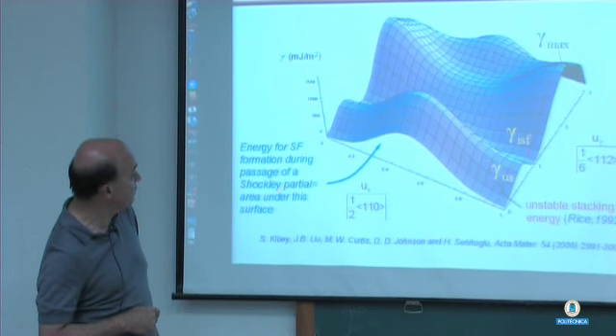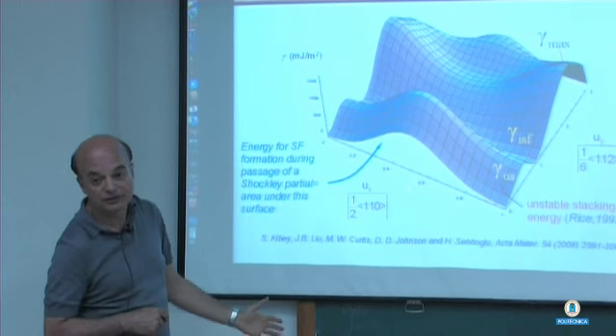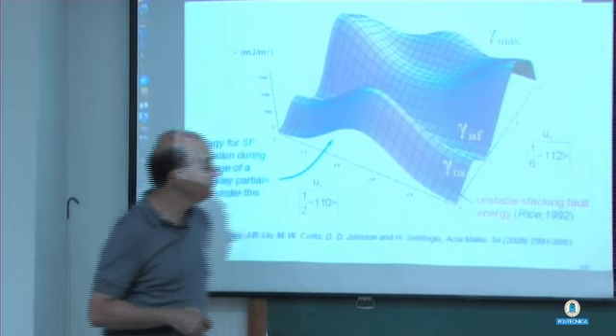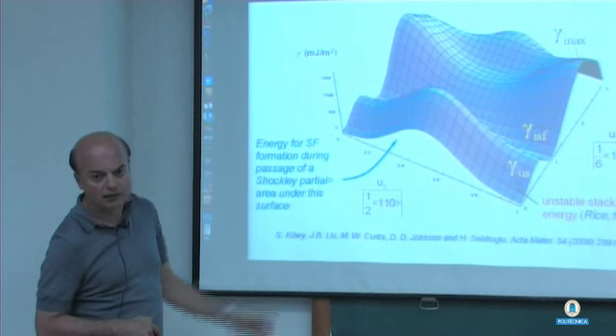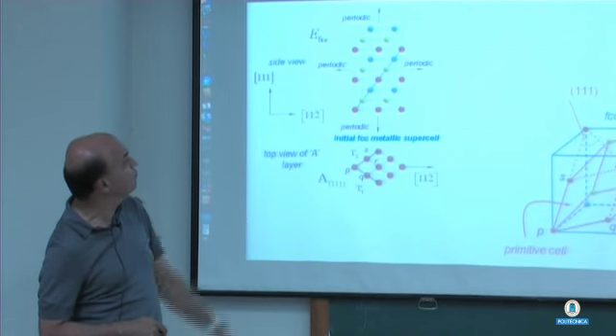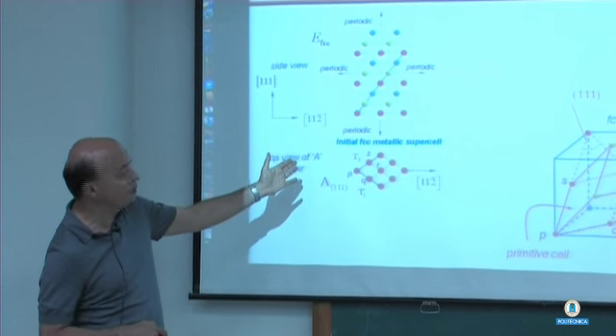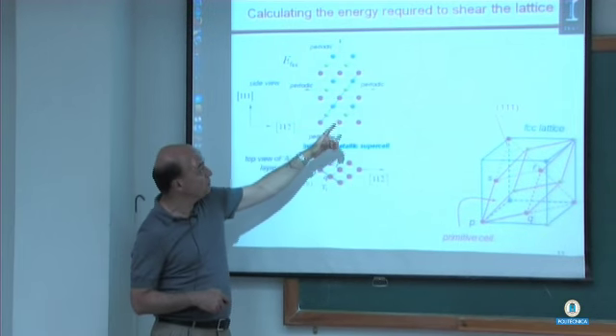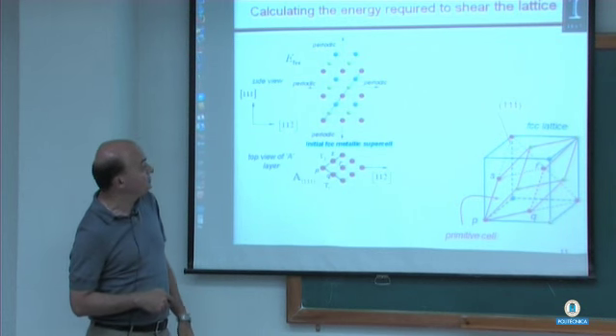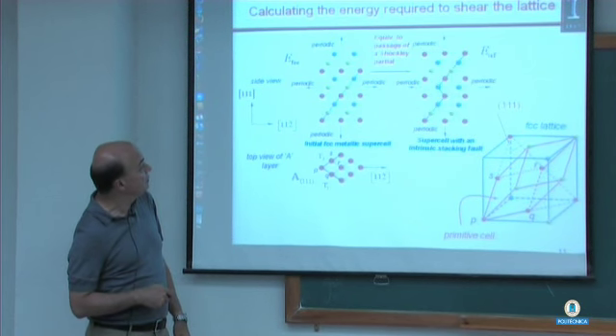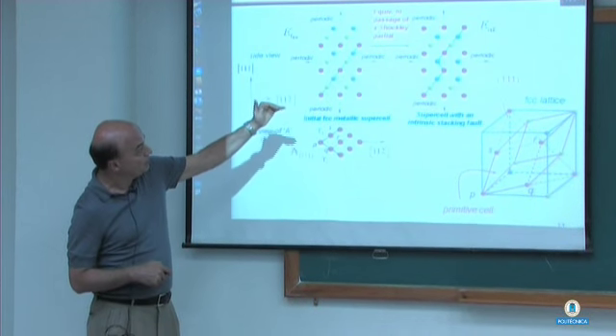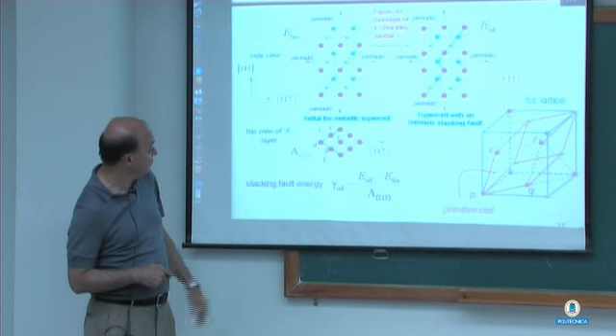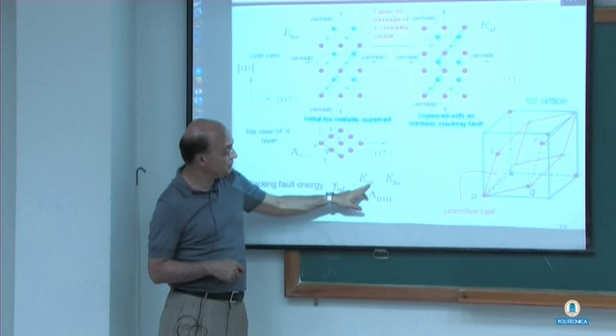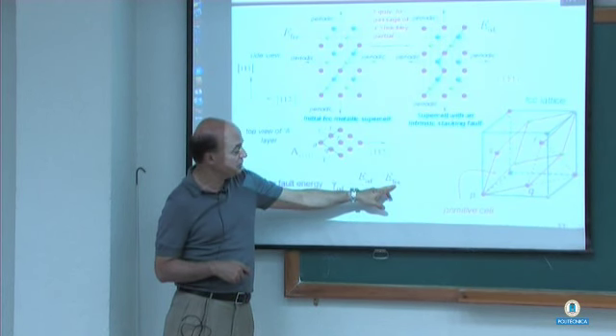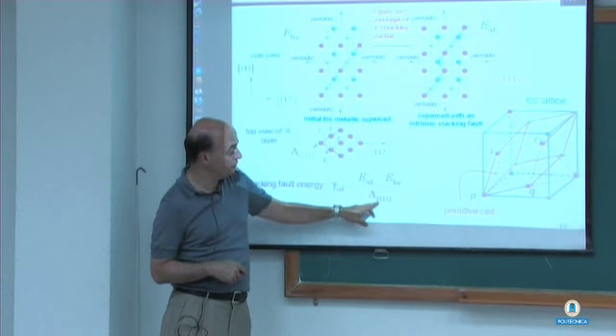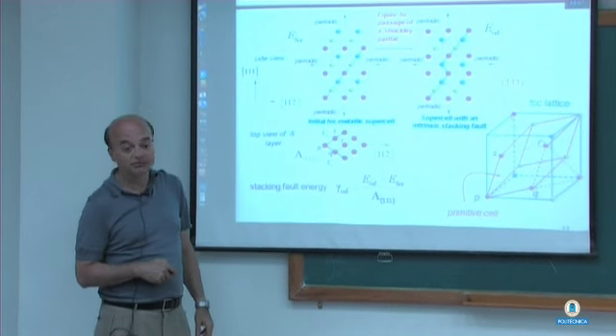Energy for stacking fault formation during passage of a Shockley partial is the area under this surface. Okay, really the area under that surface. I'll come back to that. So I talked about this a little bit. Now I would like to tell you that when we do these calculations, we take periodic boundary conditions, and we create a stacking fault by passage of a Shockley partial, and the stacking fault energy is the energy of the intrinsic stacking fault minus the energy of the ground state FCC, divided by the area of the fault plane 111, and that's the definition of ISF.